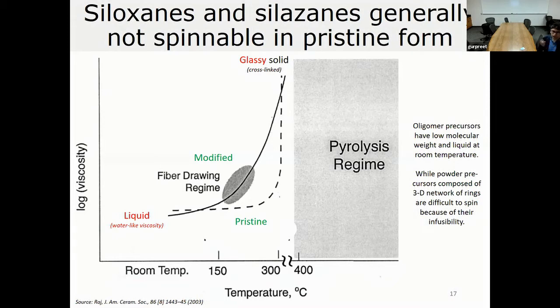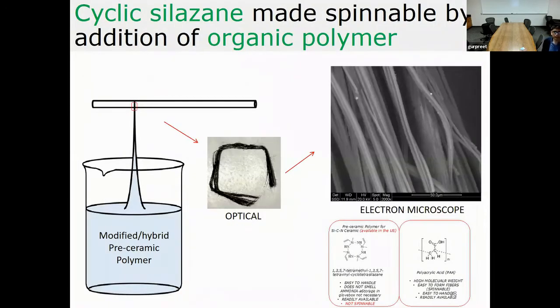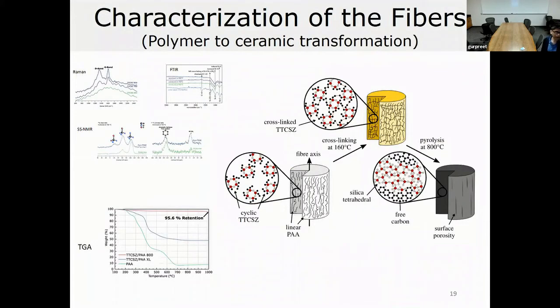But my graduate student Zongkan Ren modified the rheology of the pre-ceramic polymer by introducing a spinning agent. In this case, he selected polyacrylic acid, or PAA, which is an organic polymer. It's a linear polymer, and can be obtained in high molecular weight. He would add this to the pre-ceramic polymer, in this case a cyclic silazane, at different weight loadings. That would change the rheology and increase the viscosity by almost 200 times, and then he would draw fibers from it and characterize the fibers using a range of spectroscopy and microscopy techniques.